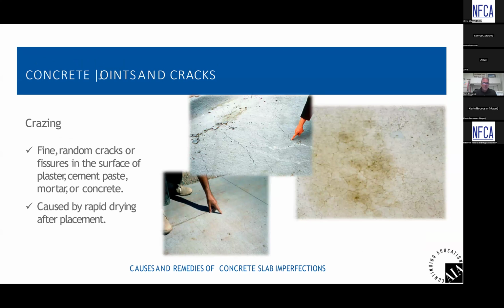Crazing. This is when you have rapid drying of concrete. I mentioned that in one of the early slides, crazing or craze cracks. If you look at the bottom left picture and the top right picture, these are superficial cracks. It could have been high airflow across the surface, sun just drying out the surface water of the concrete, things like that cause a plastic shrinkage to happen right at the surface of the concrete. These are superficial and typically have no effect on anything. But hey, raise the red flag if you see something like that, and let the structural engineer be the one to say that these are superficial cracks.